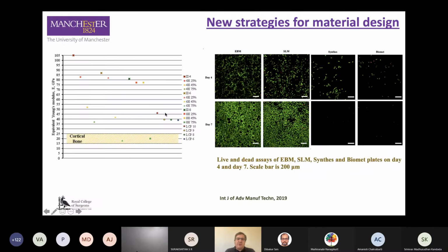And we managed to achieve a couple of designs where the plates present mechanical properties in the range of cortical bone. Those plates were made in titanium 64. We use both electron beam melting and selective laser melting to produce those plates.